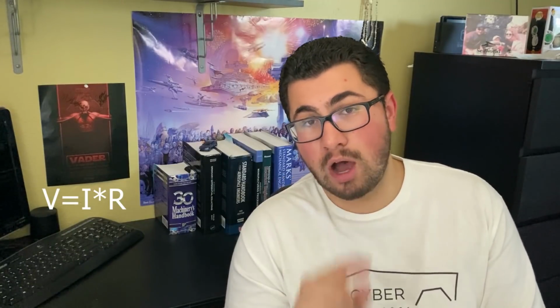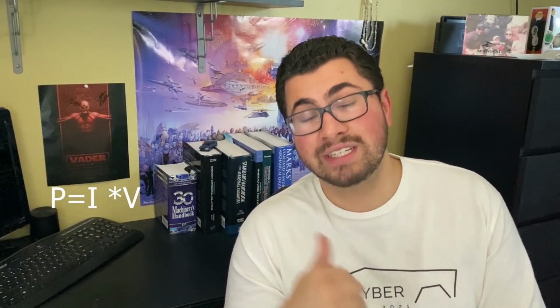So if you reduce the resistance, but you maintain the same voltage, the amount of amps that can go through it goes up. The power law when it comes to electrical engineering is that if you keep voltage the same and you increase current, you're increasing the power of the cell, which means that both on the discharge level and on the charge level of the battery, you're able to put through more power. Power is energy per second. You can put more energy in the same amount of time, or the same amount of energy in less time.